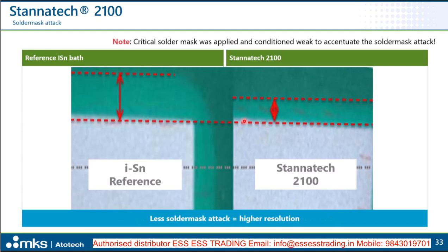And finally, it's also related to the attack on the solder masks. So we are comparing here the reference process with the Stannatech 2100 and see that we have a lower undercut to the solder mask. I don't want to make you afraid. This solder mask was applied with very weak conditions to really exaggerate the attack of the immersion tin process. So it's not the standard that we see on every panel, but this was really just to compare and to make this attack visible. And what we still see is that due to the better exchange, the undercut for the 2100 is lower.